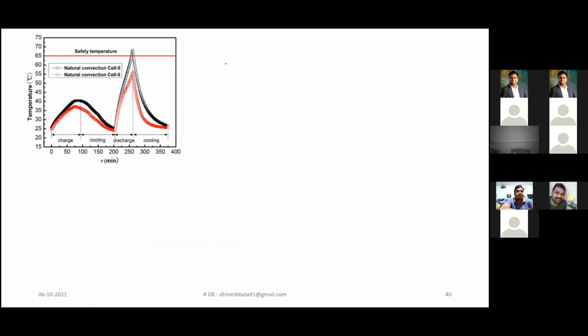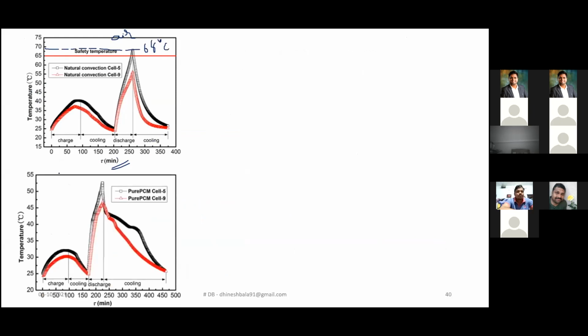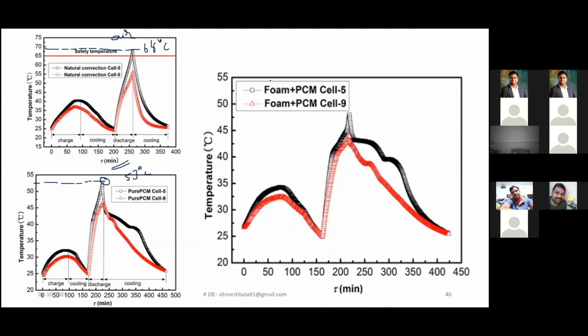And now I'll give you a comparative study of all three cases, making a comparative statement between time versus temperature limit and using air as a cooling medium. For cell number 5, the temperature is 68 degrees Celsius when air is used as a cooling medium. And when you introduce the PCM in between the cells, the temperature comes down to 53 degrees Celsius in this particular case. And when you introduce foam with PCM, the temperature steps down even further to 48 degrees Celsius. So you can see the temperature difference from 68 degrees Celsius to 48 degrees Celsius just by introducing the PCM and the foam in between this particular structure.